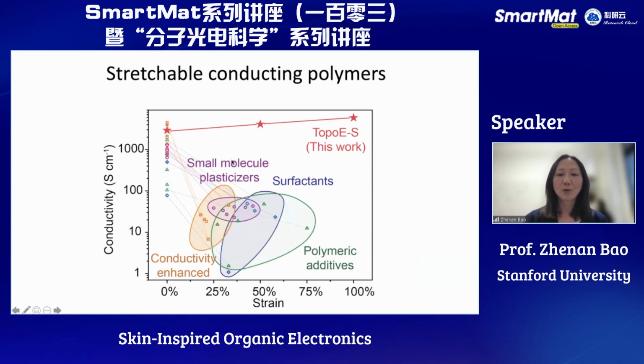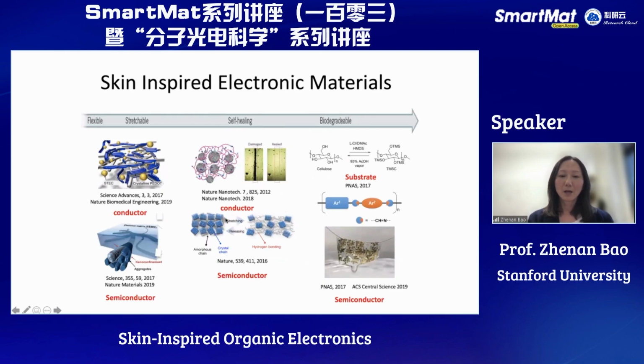So compared to many other approaches, stretchable conducting polymers already exist in the literature. But to get the stretchability, various kinds of plasticizers, surfactants, or additives are incorporated. Then these polymers typically have much decreased initial conductivity, and also decrease further with strain. But in our case, for this new conducting polymer with the nanostructure, we start with a very high conductivity already, a few thousand Siemens per centimeter, which is in a similar order of magnitude as ITO. And with strain it still maintains one of the highest conductivities. So this is very important for further development for many devices, and we are now building based on this useful material.